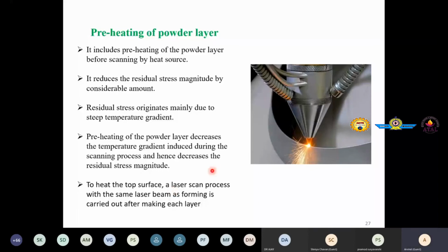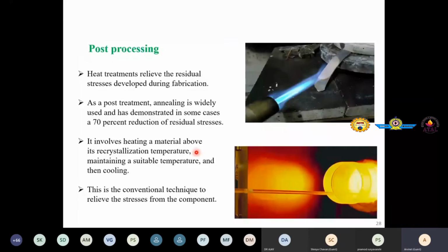Then we could reduce stresses by post-processing. We know that heat treatment relieves the residual stress developed during fabrication. As a post-treatment, annealing is widely used and has demonstrated in some cases a reduction of 70% of residual stresses. Such a heat treatment process involves heating a material above the recrystallization temperature, maintaining a suitable temperature for some time, and then cooling it with a certain cooling rate. Right? This is the traditional heat treatment we typically adopt for a formed part, or welded part, or cast part. So here also we could adopt that.